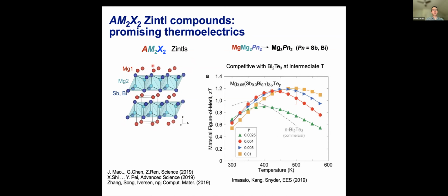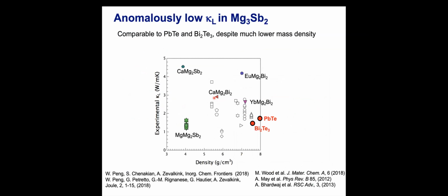And so depending on the ions you put on a magnesium 1 site, if you replace this magnesium with other elements that are larger, you can strongly modulate the thermal conductivity. But this figure here is just showing that indeed they're already achieving high thermoelectric performance. And this is in part because they have very low thermal conductivities, as is illustrated here.